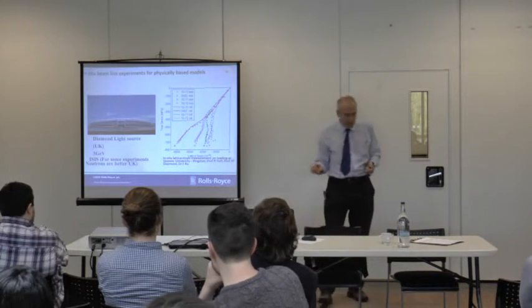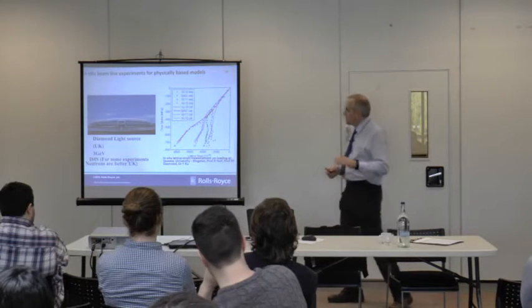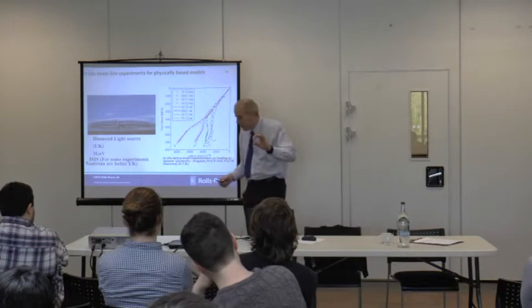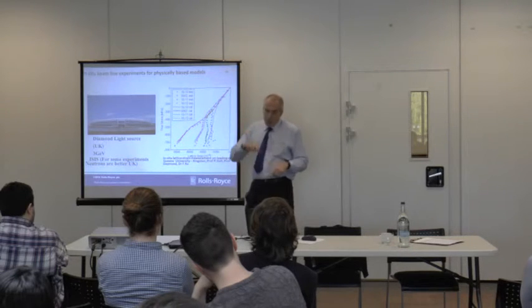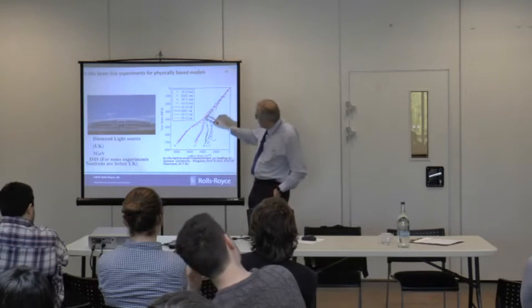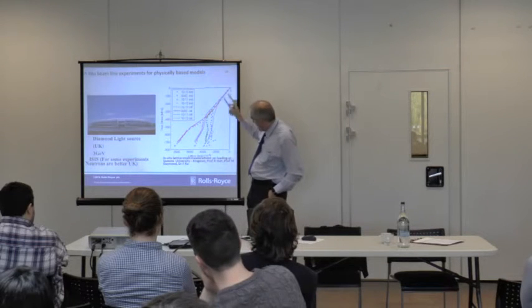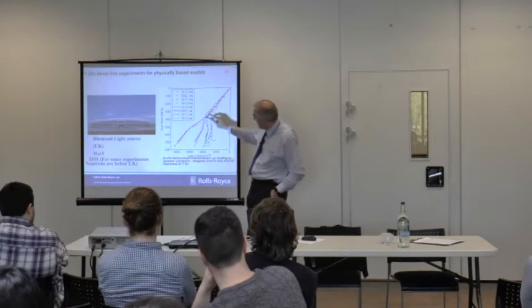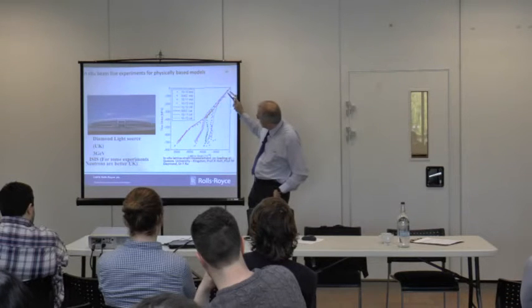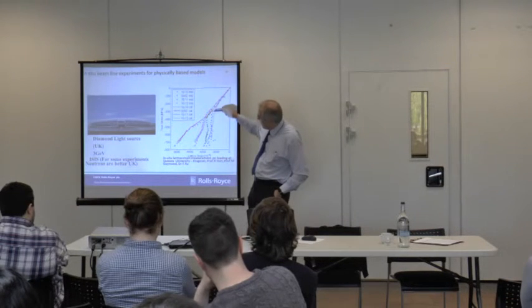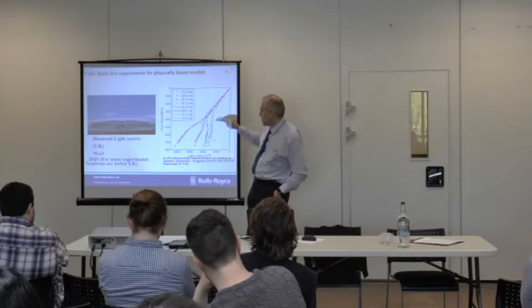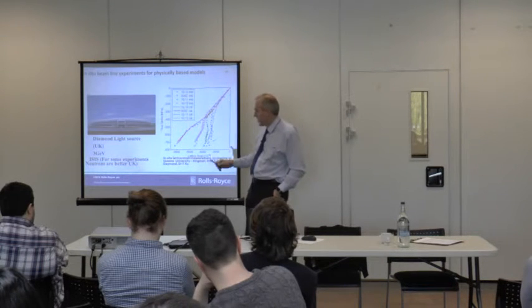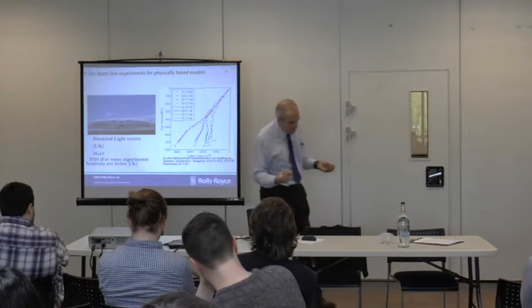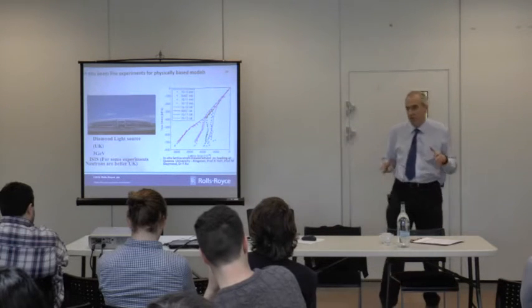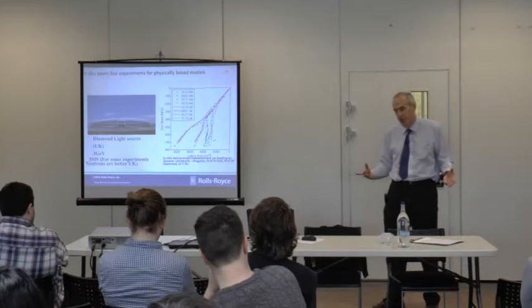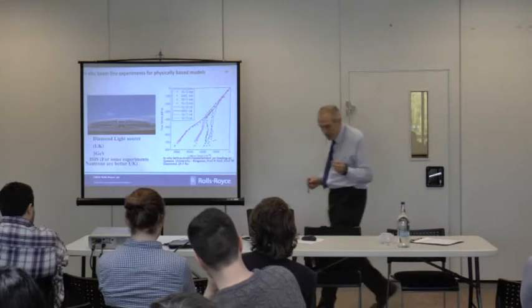We like stress, understanding stress. So what you can do is to use the atomic spacing, the lattice spacing, as strain gauges. Then when you drive the material around stress strain loops, this is in compression, this is stuff at Queen's, spent some time there as well, which is great fun. You can look at the lattice strains, see when they're loaded elastically or when they're effectively not going up in strain as a function of load, and then you can see how they all kink and interact. So that gives you family distributions for certain orientations of grains of whether they're elastic or whether they're plastic and how that changes with time, but it doesn't tell you anything about the actual individual grains.